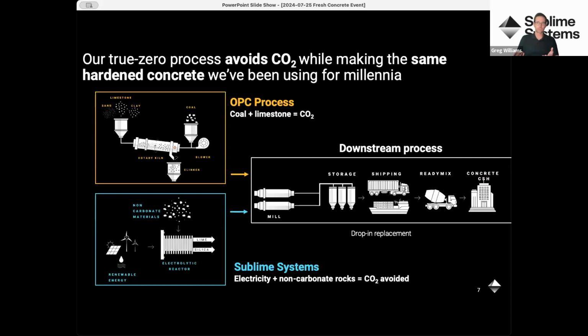Number one, we don't use fossil fuels. It's powered by carbon-free renewable energy. And we also don't use limestone as a feedstock. We use non-carbonate materials that don't have CO2 trapped in them. And so this process is powered, as mentioned, by renewable energy, and we produce two main ingredients, a lime and silica. Those are blended with some other ingredients to create Sublime Cement.